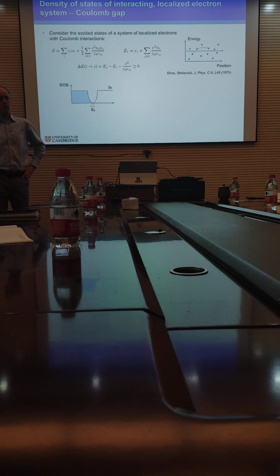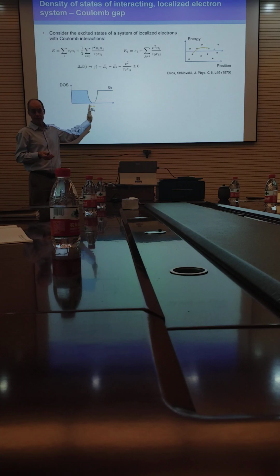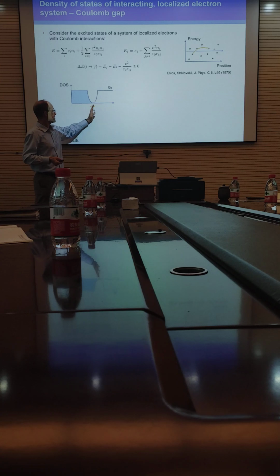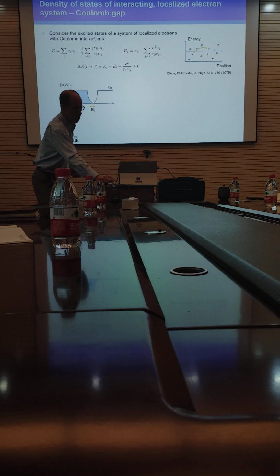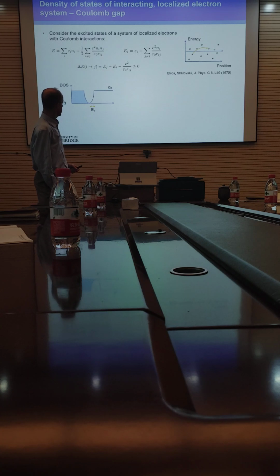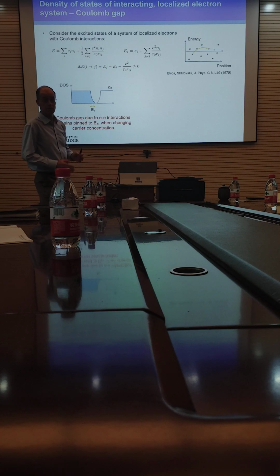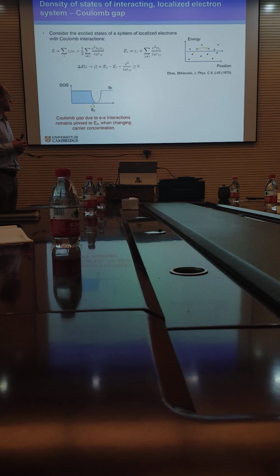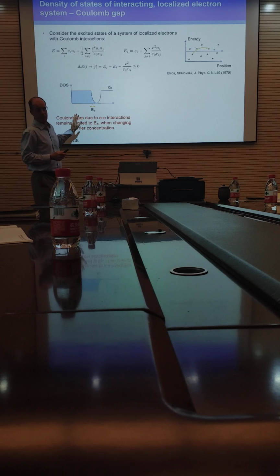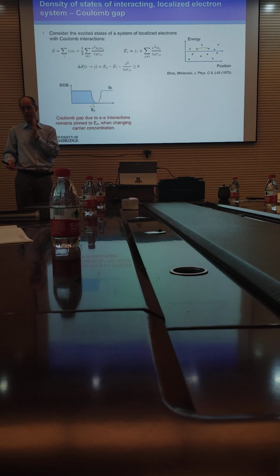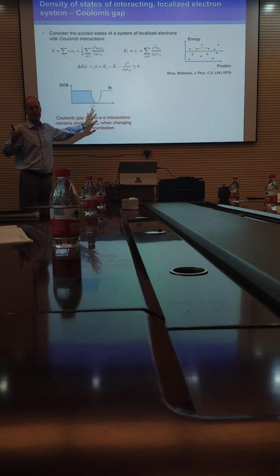The Coulomb gap has an important property, which is that as you change the electron density, it moves with the Fermi level. So if you put more electrons in and shift the Fermi level in this direction, the Coulomb gap moves with it, like this. So if I change the electron density, I would expect that the Coulomb gap remains tied to the Fermi level. So in our experiment, we are moving the electron density when we add extra charges, and this physics alone would mean that we shift the Coulomb gap with the electron density, and not much would change. So this isn't an explanation. This doesn't provide an explanation of what we see.